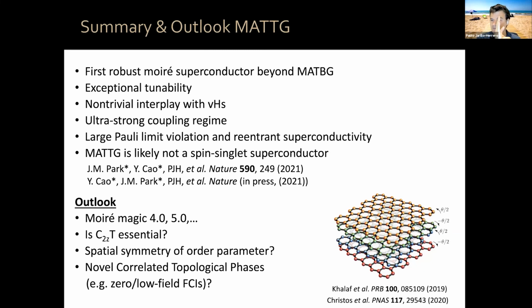Do you have a small magnetic field out of plane or in plane, which is breaking certain symmetry terms, okay? The important thing to realize is that because of these multiple degrees of freedom, spin and valley, okay, you have competition between many-body ground states, and these are actually quite close in energy, okay? So you also have nematic states, charge density wave states, etc. So theorists are now trying to find out under what conditions small symmetry breaking terms lead to many-body ground states choosing one or another configuration, okay? And this is not yet completely clear experimentally, but theories are slowly converging, okay? It seems like once you accumulate the different experiments, there are different experimental signatures in one or another direction, and certain states are more favored than others, okay? But the important thing I want you to take away from my talk today is that at each of these integers, there's a process of spontaneous flavor polarization, okay?